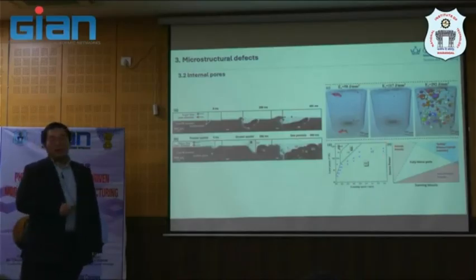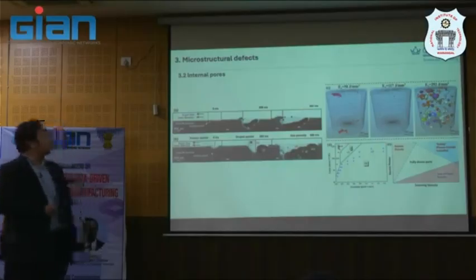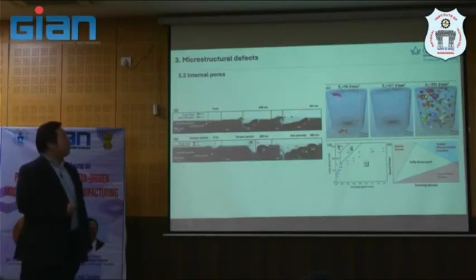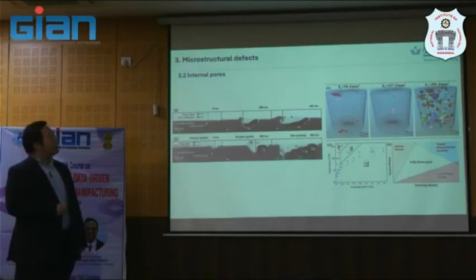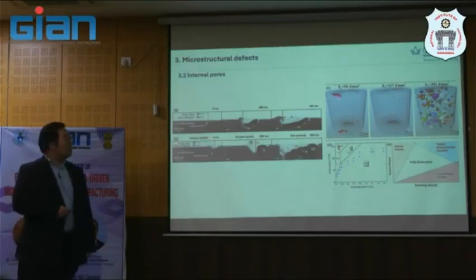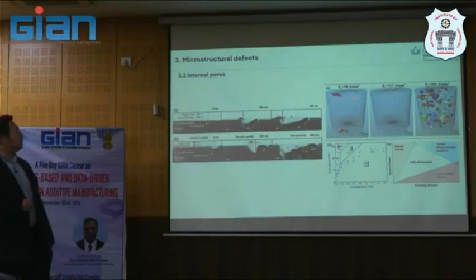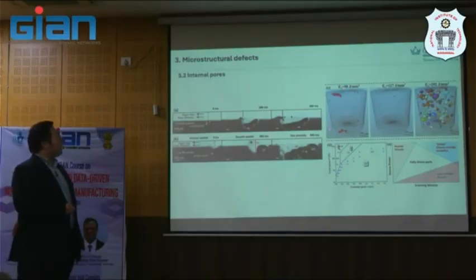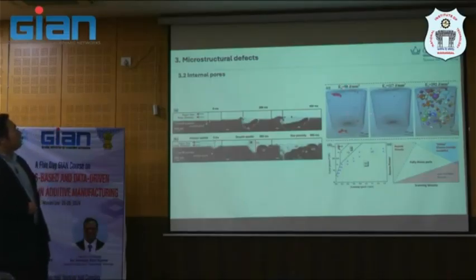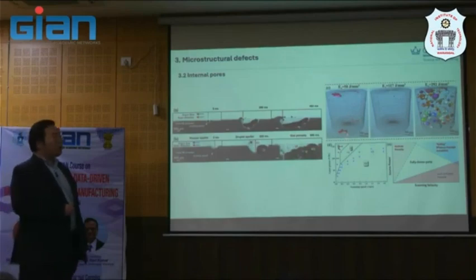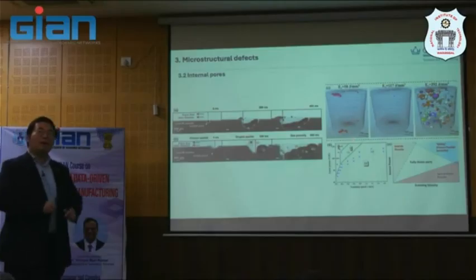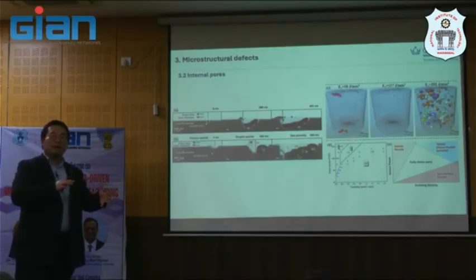But another, in terms of microstructure defect for porosity, as industrial or engineer, we also want to understand these as a function of process condition. So from the low energy density, intermediate energy density, or high energy density, you will see from this XCT, which is X-ray micro CT, micro X-ray tomography here, you will see this is more lack of fusion feature.